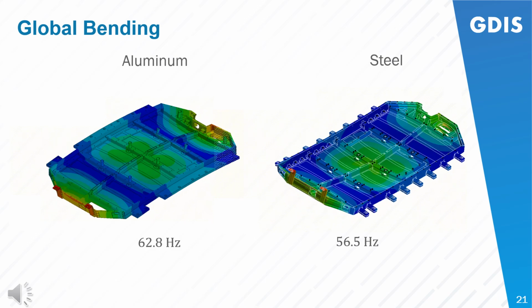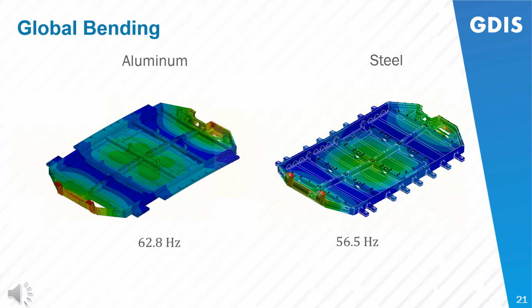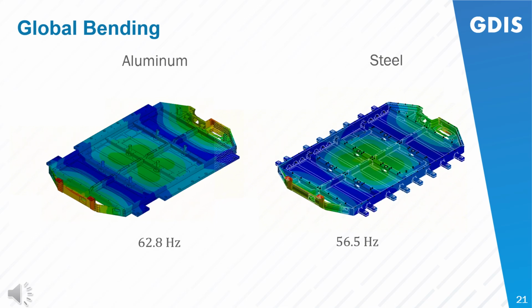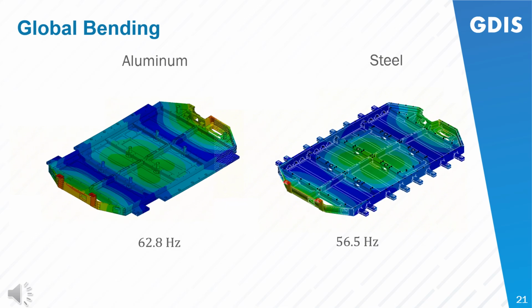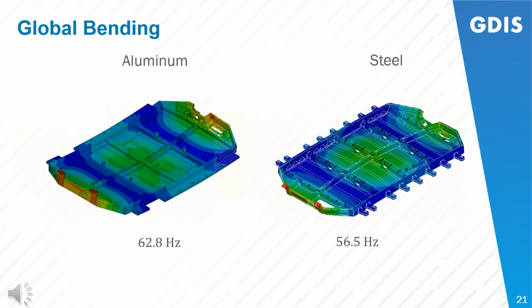And finally, this is a comparison of the global bending mode between the steel and the aluminum, steel on the right-hand side, aluminum on the left-hand side. You'd note that both modes are fairly similar, with a minor difference because, of course, the steel has discrete outrigger brackets as opposed to the continuous ledge that the aluminum construction has.